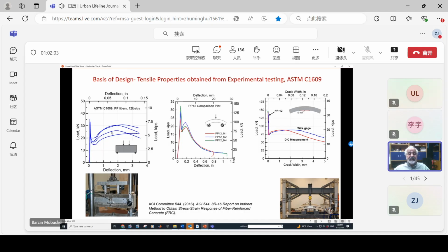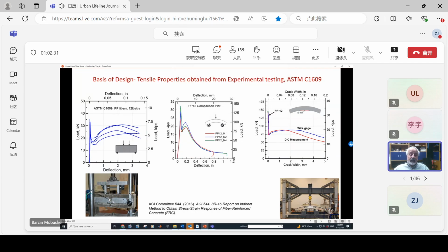And the response that we get is again the same. Test some standard flexural beams, measure the material property, and you can test the large scale and go from the small scale to the large scale. So this is great for design if I have enough fibers in there to be able to carry the load based on the stresses that are allowed. This has been published. This report was published in 2016, and the method for back calculation.